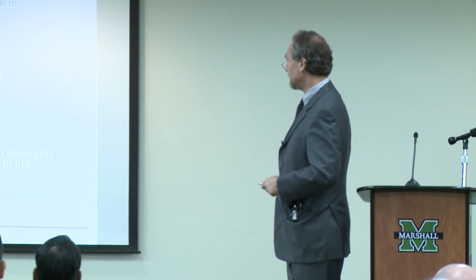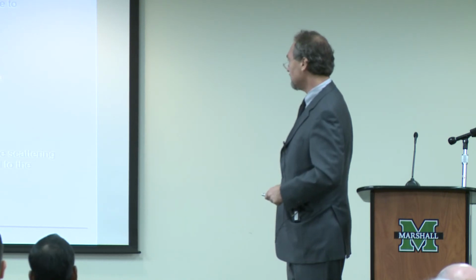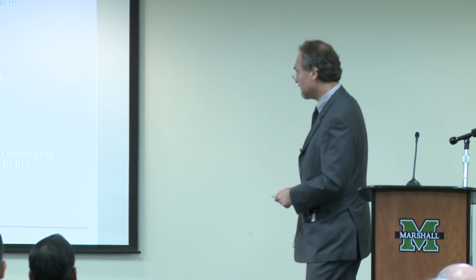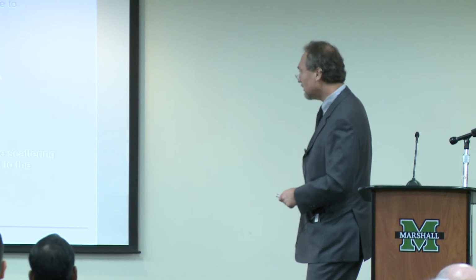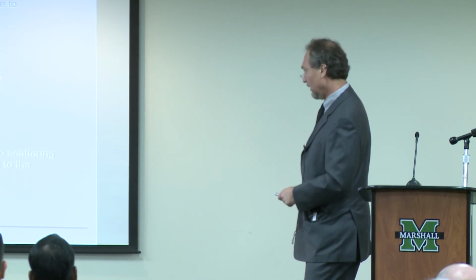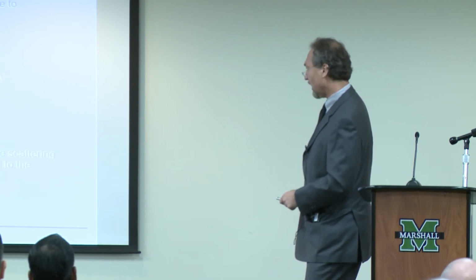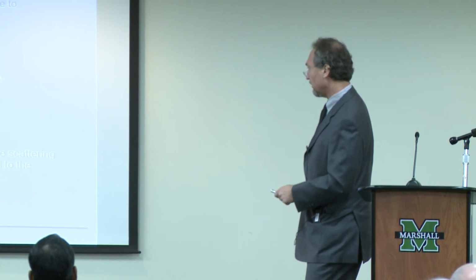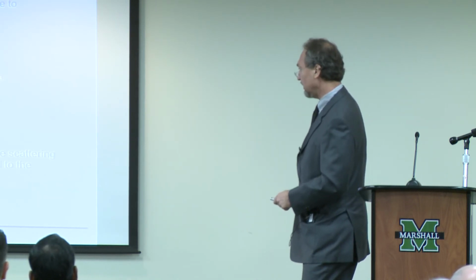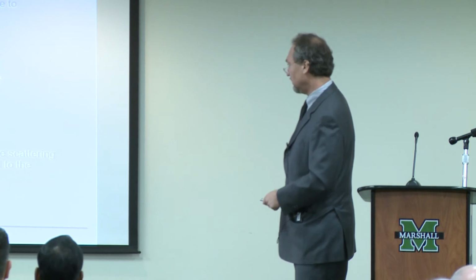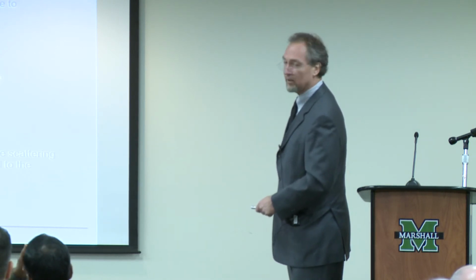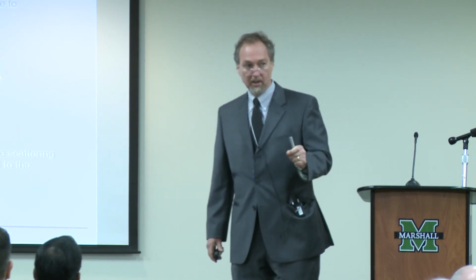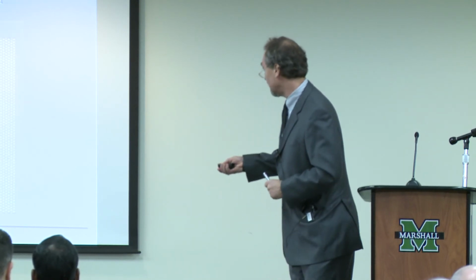So I can calculate the scattering rate. Putting it into the phonon attenuation, if d is the thickness of your layer which has these defects, tau is the scattering time, the inverse of the scattering rate, and v is the speed of sound, then if you put these in, I get about 8% for a 10 nanometer thick layer. So it's just in the ballpark. And I guess I have to wrap up.